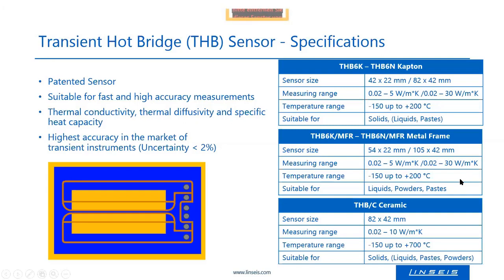For a higher temperature range, the ceramic sensors can be used. The thermal conductivity range is not as high, because the time constant of the ceramic sensors is longer, so the time resolution is not so good compared to the Kapton sensors. That's the reason why we can measure with the ceramic THB sensors only up to 10 watt per meter Kelvin. But they are suitable also for solids, liquids, pastes, and powders up to 700 degrees Celsius, beginning at minus 150 degrees Celsius.